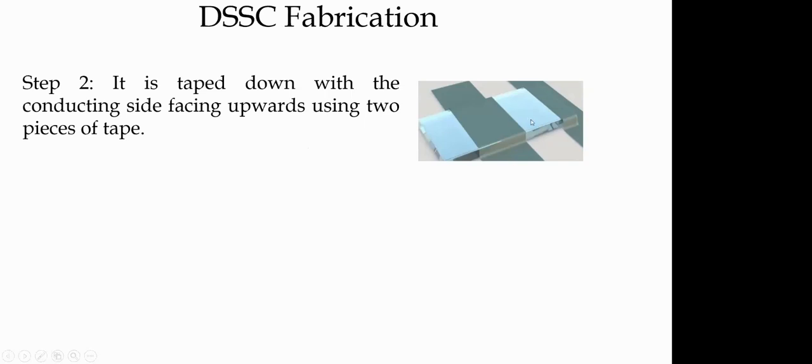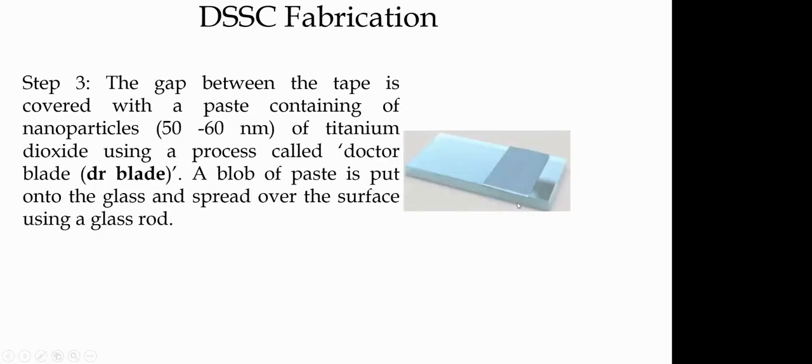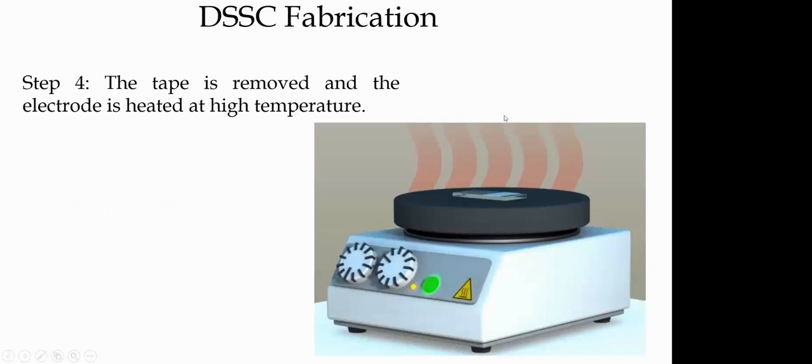Just like you pour the liquid slurry, and then you take a spatula or a blade and drag it to the other end, you will get a uniform layer. The thickness of these layers is around a few micrometers, 3 to 4, 5 micrometers. That is there, right? So once you have fabricated this layer, you heat it